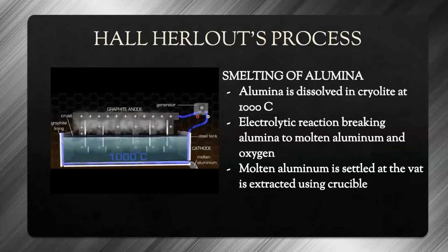During electrolysis, the electric current passes through the pots where the chemical reaction occurs. The current flows from the anode through the aluminum and cryolite solution to the cathode and the next pot. The temperature in this process must be maintained at 970 degrees Celsius to 1000 degrees Celsius to split the alumina into molten aluminum and oxygen.